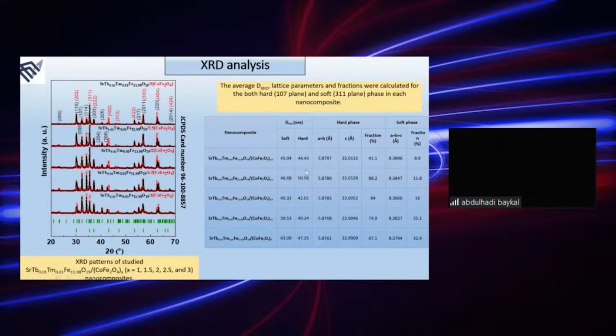Okay, and also for the hard phase, we can calculate the cell parameters. Also, with the help of the software program that we apply for the phase analysis, we can deduce the fraction of hard and soft in the structures. We can deduce the fraction of hard and soft in every nanocomposite. Okay, and then we calculated the cell parameters A and C for the hard phase, which means hexaferrite. We also calculated the cell parameters for the soft phase.